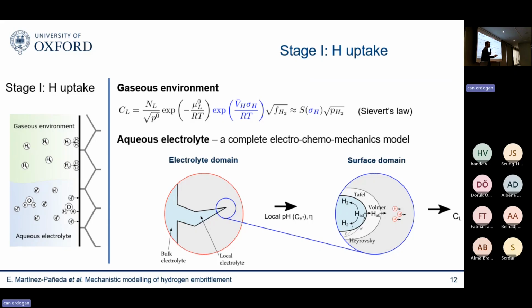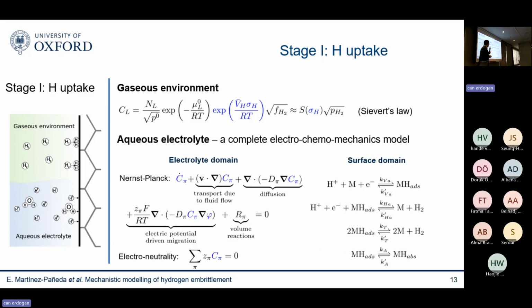One is that not only do you need to resolve the surface reactions, but you also need to resolve the electrochemistry of the electrolyte. Because, as anyone in the corrosion community will tell you, the conditions of the electrolyte in the bulk, where an engineer can measure them, are very different to those inside of occluded electrochemistry, such as cracks or defects. So that's a challenge. I mean, the good news is that we know how to express mathematically, I would say from mesoscale first principles, what happens there. So we have